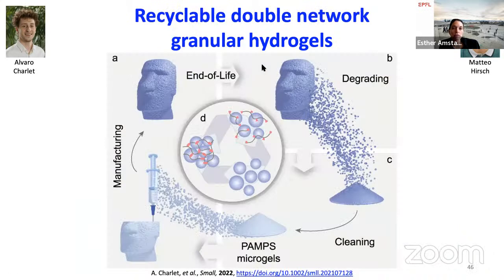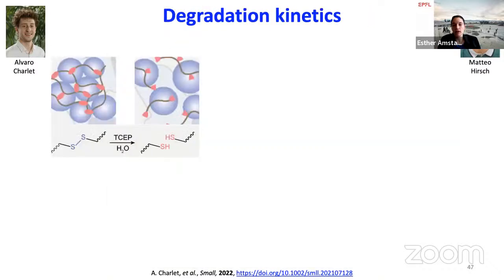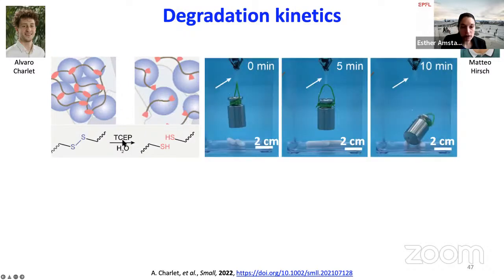Now, if you think about these materials and about sustainability of materials, which becomes increasingly important, I thought this is a material that is actually quite well suited for recycling, because as soon as you decompose the percolating network, the material will disassemble into individual building blocks, into particles in this case, and you should be able to recycle them. To show feasibility, we formed a percolating network through disulfide bonds that can be cleaved through the addition of some chemicals to be decomposed into its individual building blocks.